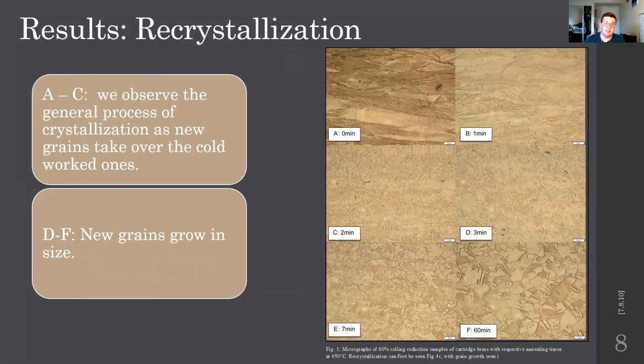Now, looking at the recrystallization, we looked at the 60% rolling reduction for the most drastic and easy to observe changes in grain size. So from A to C, you see the first process of recrystallization where at 1 minute, you have tiny dots all throughout the grains. Those are baby grains that are starting to recrystallize. In part C, you can see that it's almost entirely baby grains with only a few of those elongated grains from cold working. And from D, the new grains have basically taken over. Basically, all of these are free from stress as we had hypothesized.